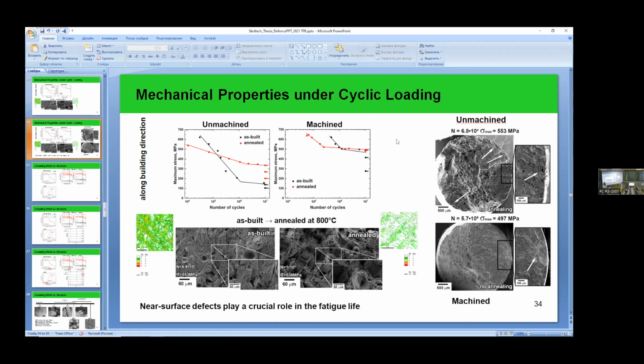So is this really a true indicator of the endurance limit? Is it because this is heavily influenced by the presence of defects that you are getting this variation at the endurance limit? In the case of these 3 data points, we applied a stress load of approximately 200 megapascal, and we achieved this number of cycles. We stopped the testing without fracture, without damage to the samples. Then we moved to higher stresses, and that's why we achieved these additional points. So it didn't break, and I think that is exactly the endurance limit. Got it. So maybe in future, after additional cycles, they will break, but we don't know. It's somewhere maybe at 10 power 8 or 10 power 9.